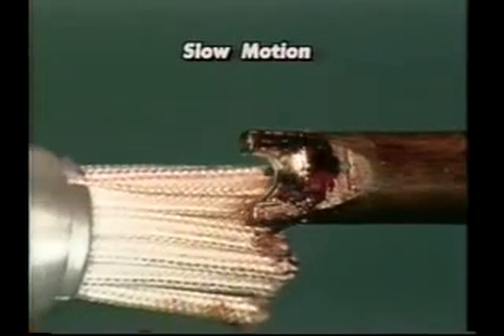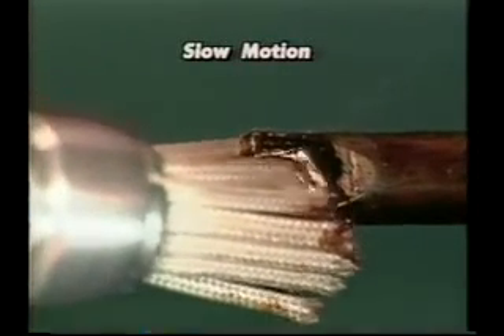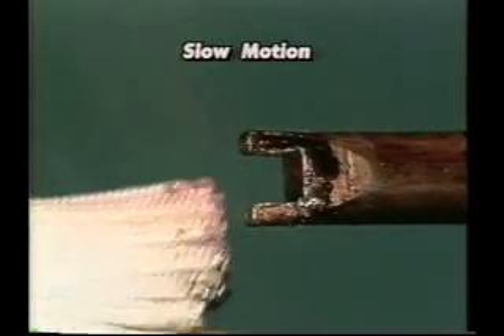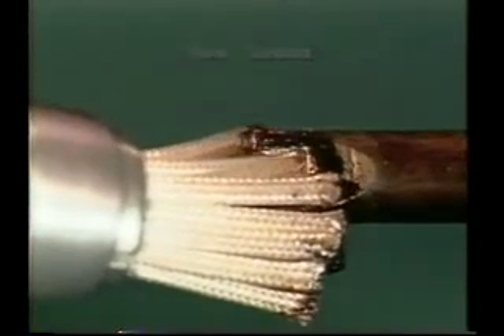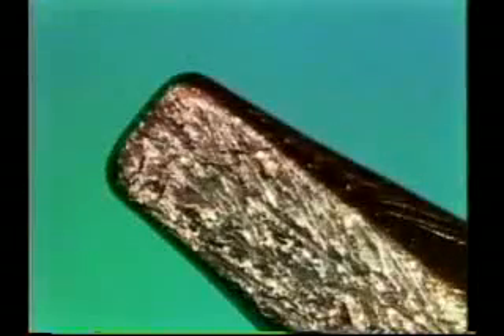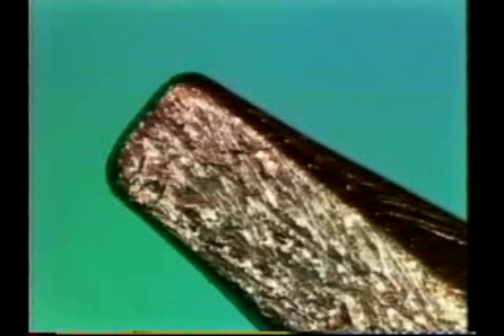Since this particular tip has a cavity, it will require special cleaning and tinning procedures. First, we'll need to remove any solder from inside the cavity of the heated tip with a non-abrasive fiber tool. It's important never to use a wire brush for any tip cleaning procedure, since the wire will scratch all the way down to the base metal. This would allow oxidation to form on the base metal and severely decrease the useful life of the tip. After cleaning the tip with the fiber tool, the next step is to remove any oxidized solder by shocking the tip on a wet sponge.